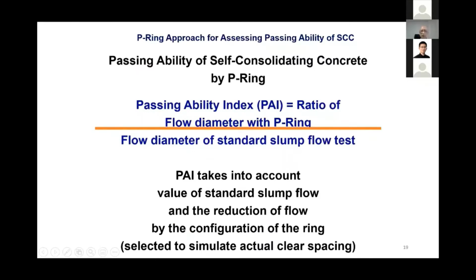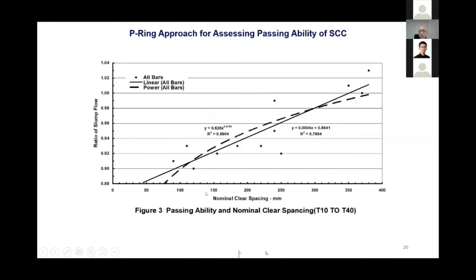So the passing ability index is the flow diameter with the P ring as against the flow diameter of the standard slump flow test. How much we have lost. So that is a ratio. Now this ratio can then diminish with time, and we now have a control, not only go, no go, but actually decide for ourselves what is a practical limit that we really cannot tolerate. Because in practice, there's always a degree of tolerance that we want to apply.